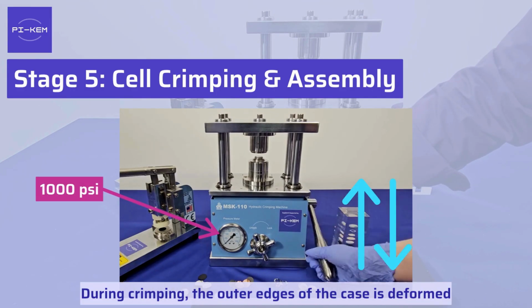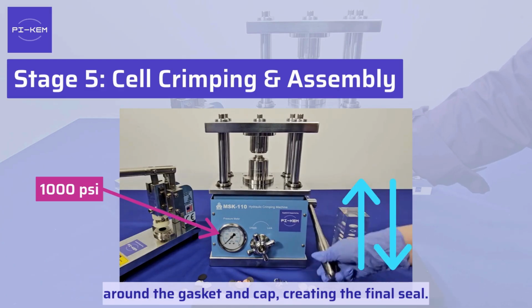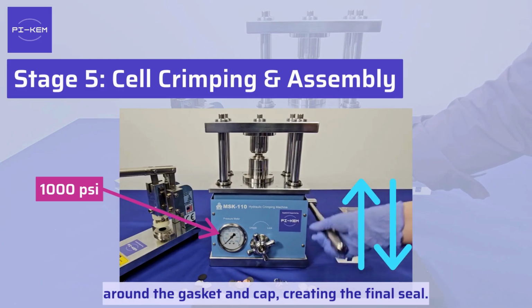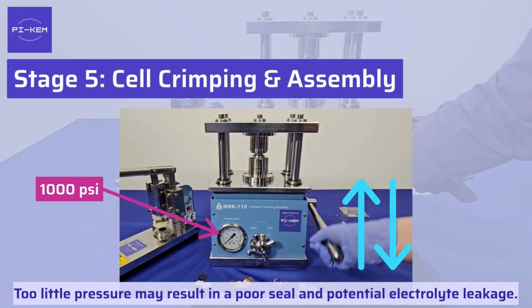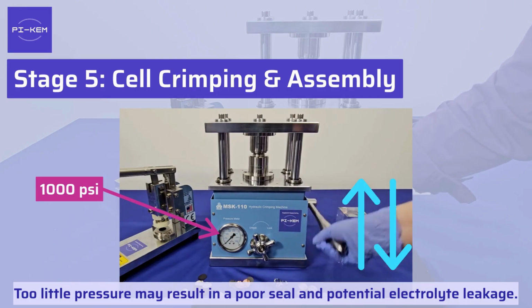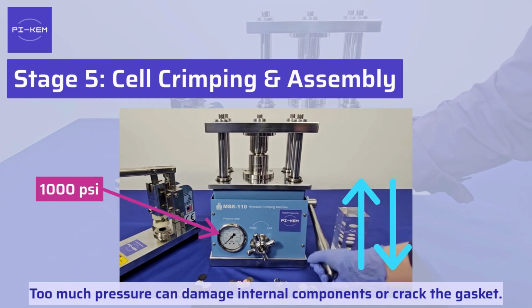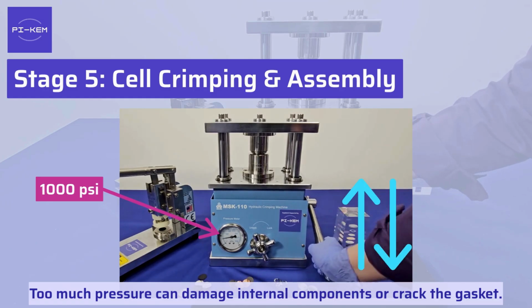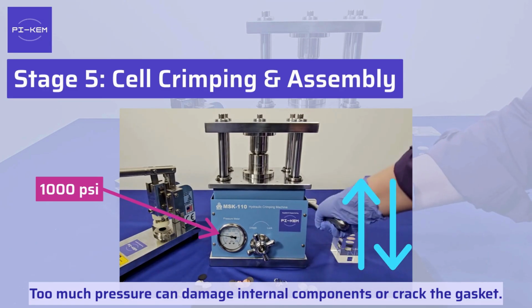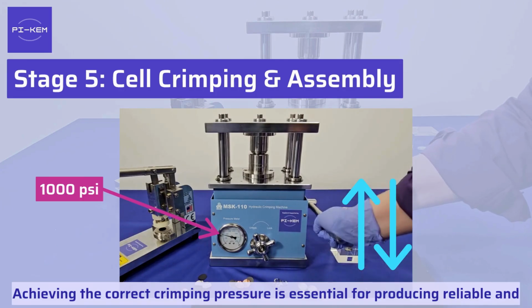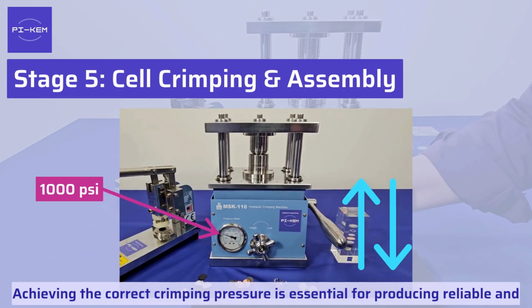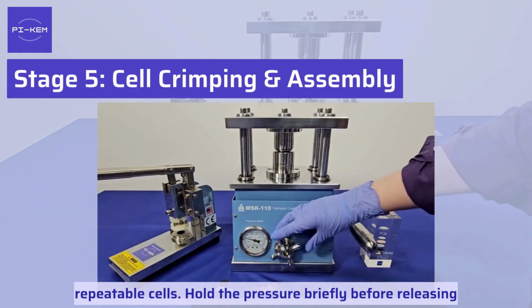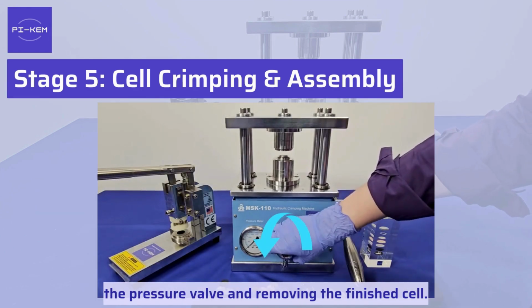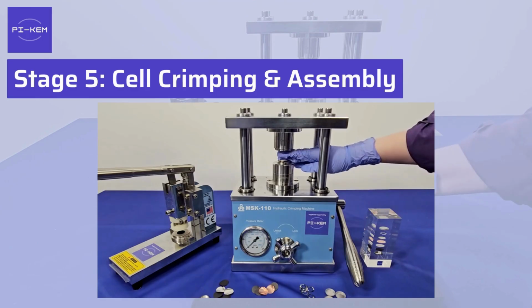During crimping, the outer edges of the case are deformed around the gasket and cap, creating the final seal. Too little pressure may result in a poor seal and potential electrolyte leakage. Too much pressure can damage internal components or crack the gasket. Achieving the correct crimping pressure is essential for producing reliable and repeatable cells. Hold the pressure briefly before releasing the pressure valve and removing the finished cell.